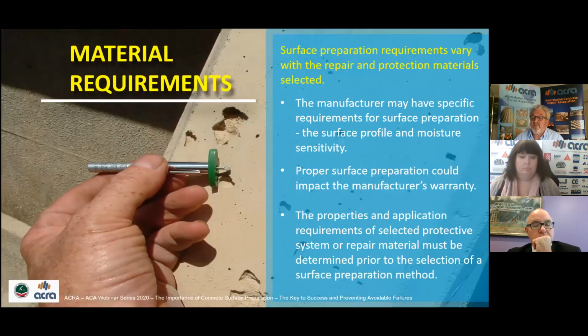The material requirements that I mentioned before, it's not just our surface preparation. The material specified, there's a few things we have to take into account there. And surface preparation requirements will vary depending on what the repair or protection materials that have been specified are. Manufacturers of the system will have specific requirements for surface prep, including profile and moisture sensitivity, and they need to be consulted. Proper surface preparation can impact the manufacturer's warranty. So therefore, the application requirements of surface must be determined prior to the selection of a surface preparation method.